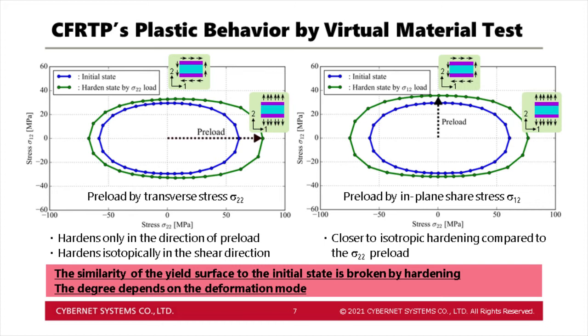The green one is characterized by a large overhang in the pre-stress direction. On the other hand, in the case of pre-stressing by shear component, although there is no serious distortion compared to the results from transverse stress, it does not show the same characteristics of free isotropic hardening behavior as a resin. From the above, it was confirmed that even if the resin has isotropic hardening behavior, the UD composite has anisotropic hardening. Moreover, this behavior is dependent on the stress state.